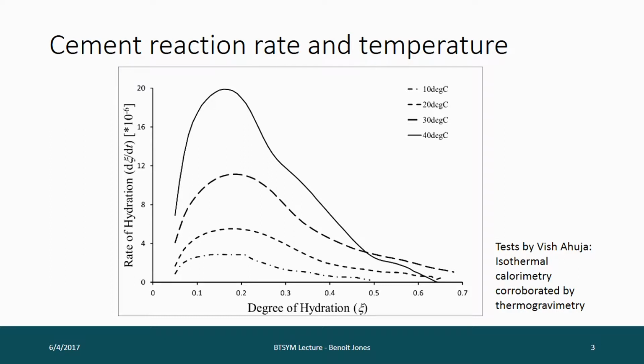And you can see that the rate is doubling. And it's doubling pretty much consistently across the whole of the hydration. And that's a really valuable property. Because if you were to find a relationship that takes account of temperature, you could make all those curves line up and have one characteristic curve. So we'll be doing that later.